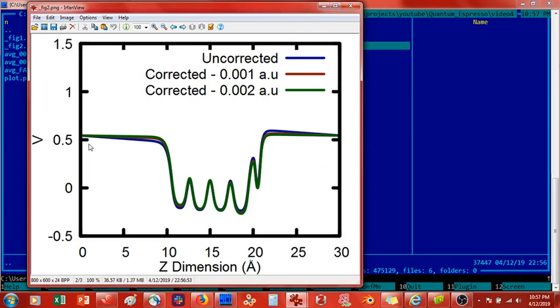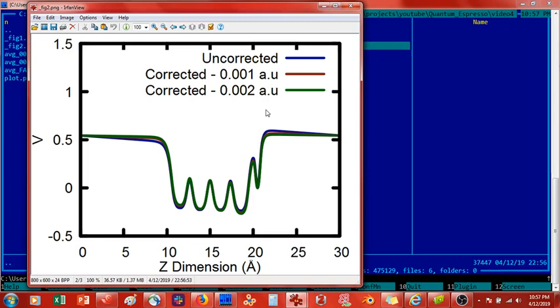And I would say that actually this one looks good. I would say that the green line looks good enough. And so you can tell here, for example, the dipole correction in here made a big deal. You can see that with the dipole correction, you get I would say a quantitatively different value for the potential of this layer. And although this isn't the biggest dipole, I imagine, that you need to correct for when you're doing actual research. And you're depositing like entire layers, especially like layers of cesium on surfaces, you can significantly change the work function of your surface and you will create a pretty large dipole, and you'll need to correct for it.